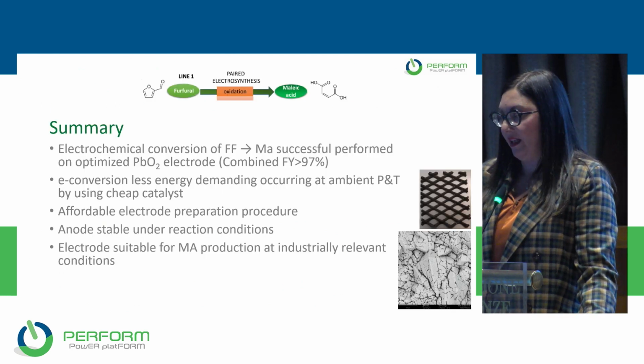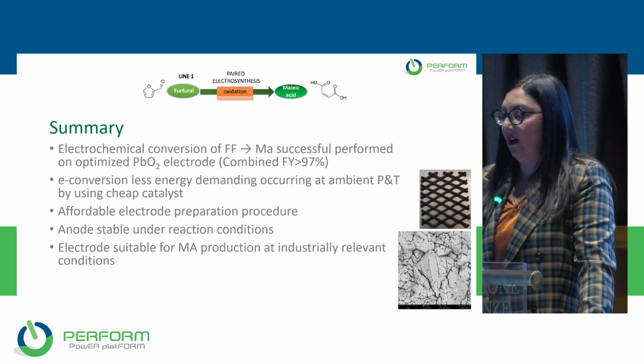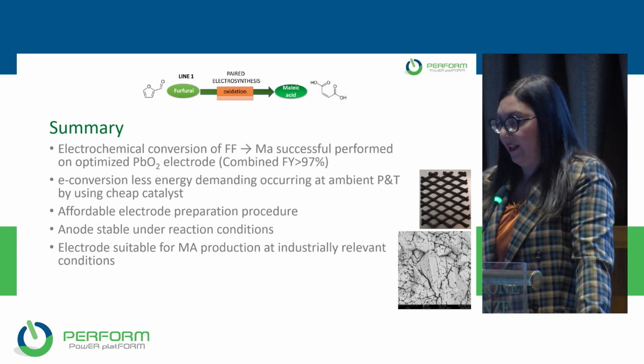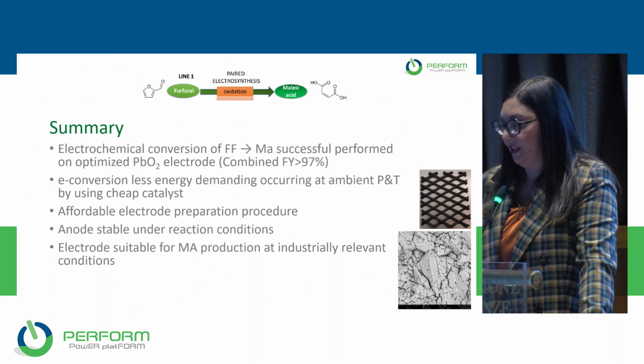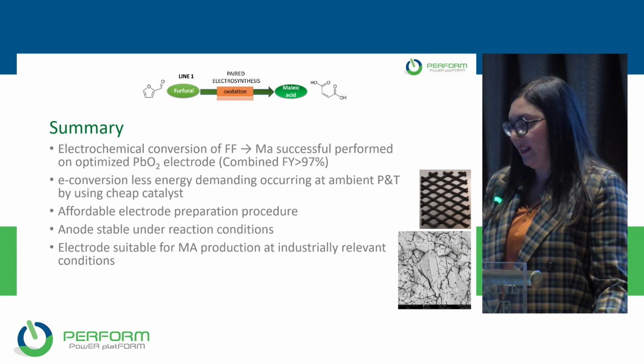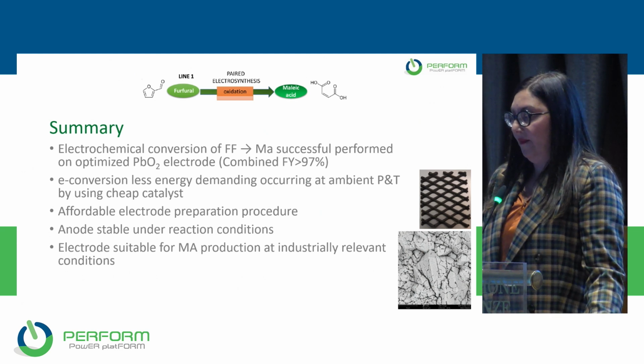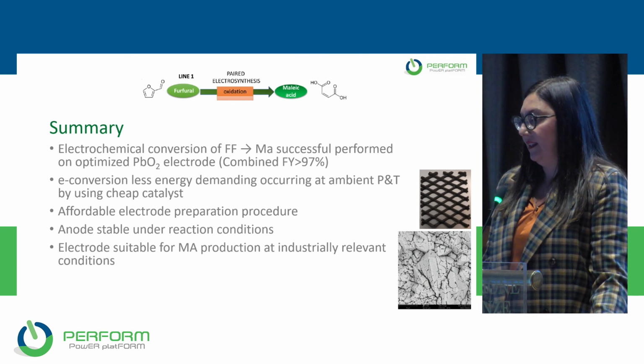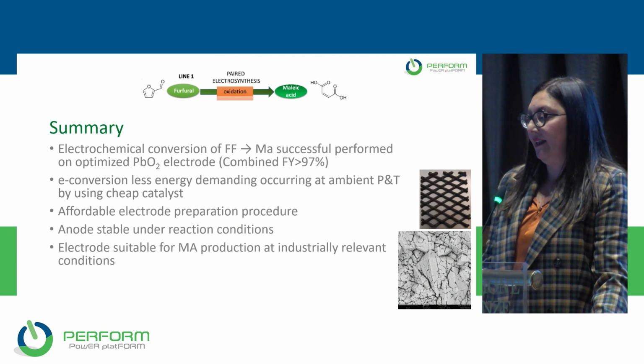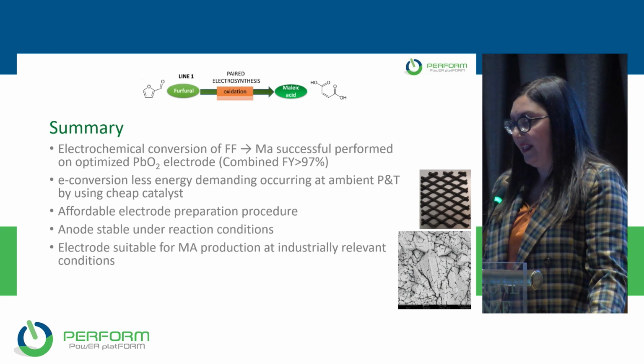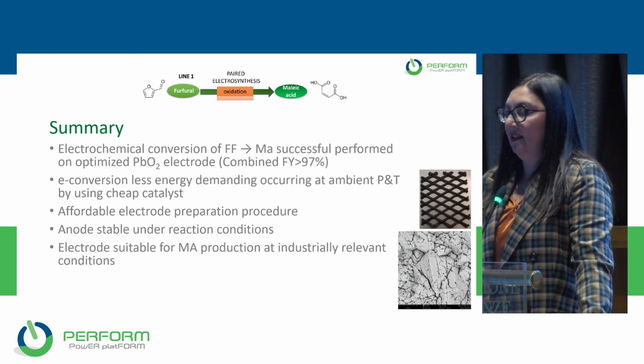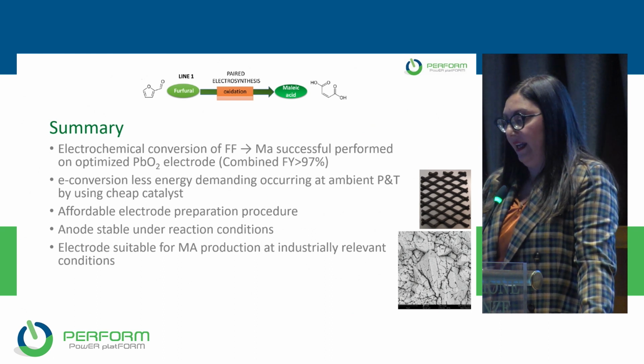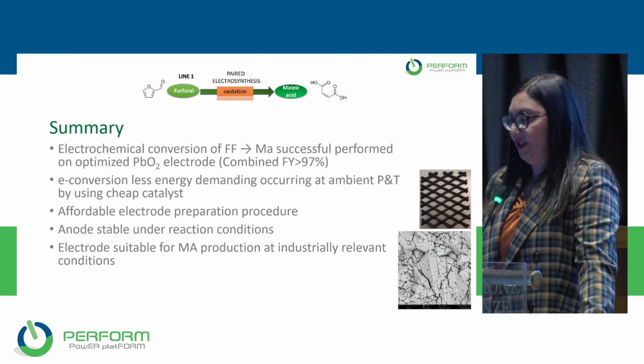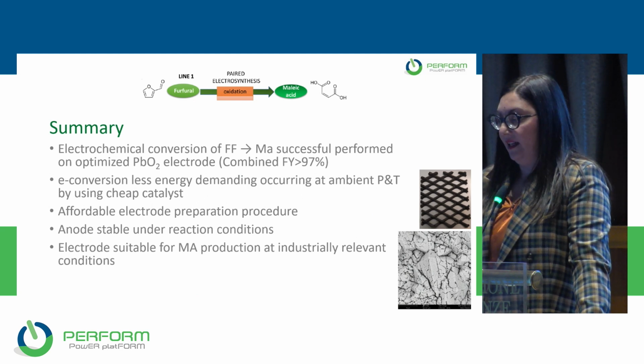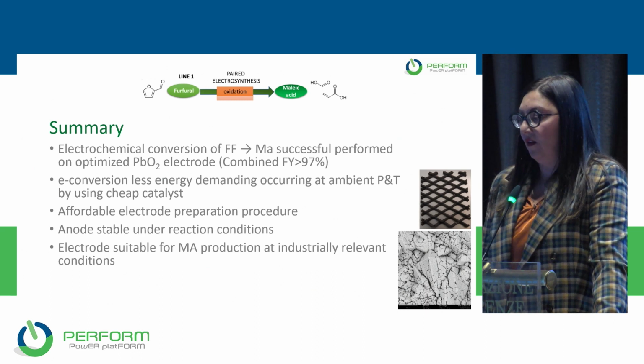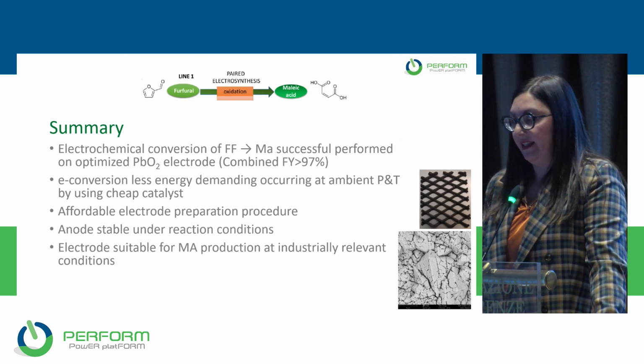In summary, the electrochemical conversion was successfully performed on an optimized lead dioxide electrode, reaching a combined Faradaic efficiency higher than 97%. This type of conversion is less energy demanding, occurring at ambient pressure and temperature, and uses a cheap catalyst material. The preparation procedure of the electrode is affordable, and the electrode is stable under reaction conditions. And finally, we can conclude that this type of material is suitable for maleic acid production at industrially relevant conditions.